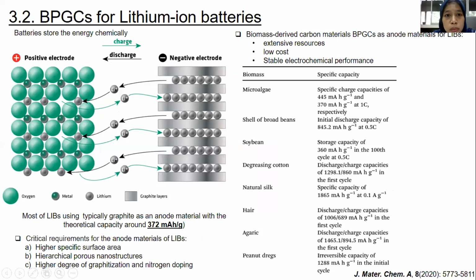And for lithium-ion battery, the critical requirement for anode material is that it should have a higher specific surface area, hierarchical porous nanostructure, and a higher degree of graphitization and nitrogen doping. I will talk faster because the time is limited. And the biomass-derived carbon material BPGCs are used as anode material due to the extensive resource, low cost, and stable electrochemical performance.